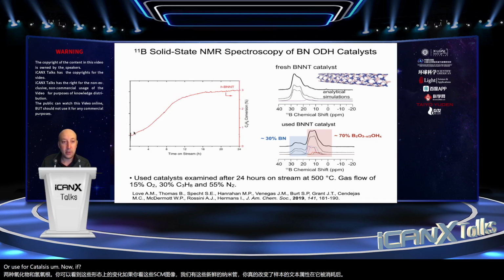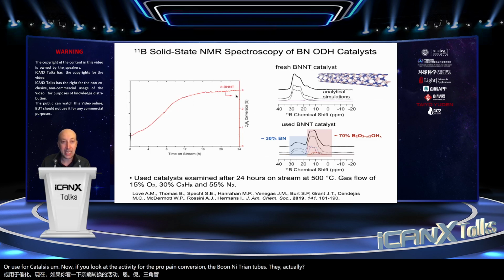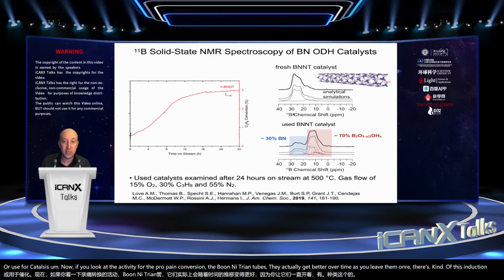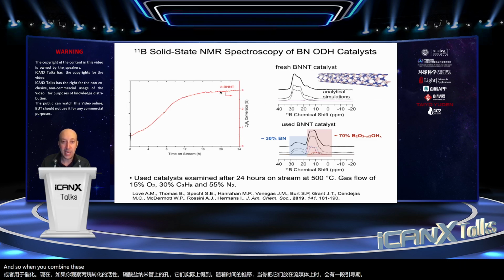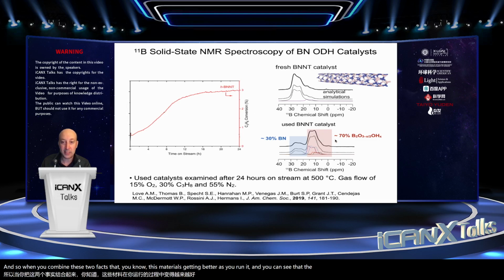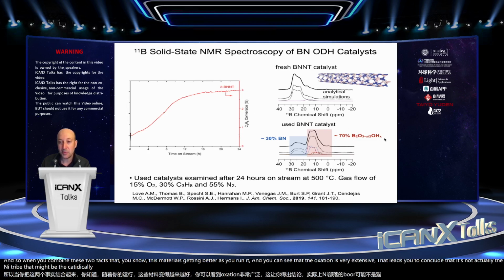Now, if you look at the activity for the propane conversion, the boron nitride nanotubes actually get better over time as you leave them on stream. There's kind of this induction period. And so when you combine these two facts, that this material is getting better as you run it, and you can see that the oxidation is very extensive, that leads you to conclude that it's not actually the boron nitride that might be the catalytically active species, rather it's the oxidized surfaces of these materials.